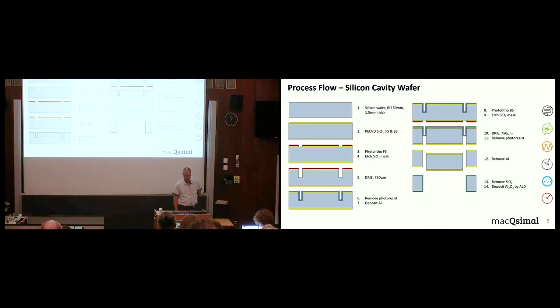Then we remove the photoresist and deposit a thick aluminum layer. We do, in step 8, another photolithography on the back side, pattern the oxide, and use this double mask again to etch a 750 micrometer deep trench from the backside onto the aluminum layer. Then finally, in step 12, we remove the aluminum, which makes all these central cylinders fall out. We remove the oxide, and then we deposit by ALD process an aluminum oxide layer, which acts as a diffusion barrier for the rubidium.